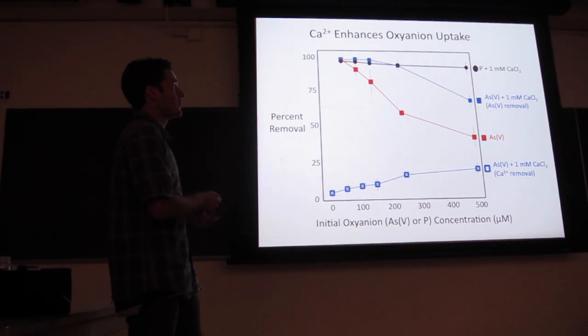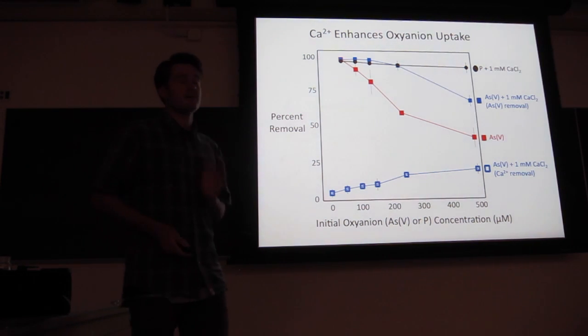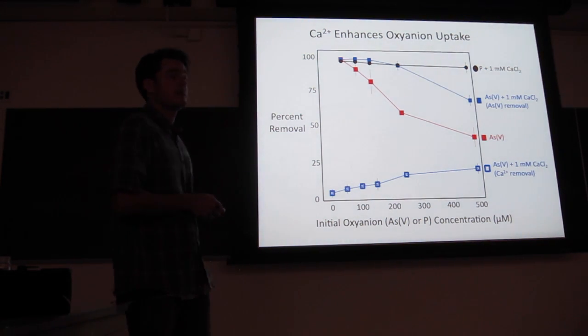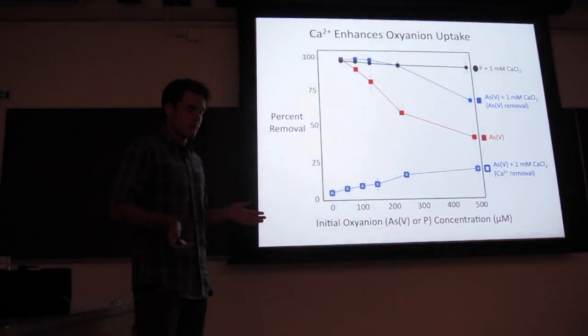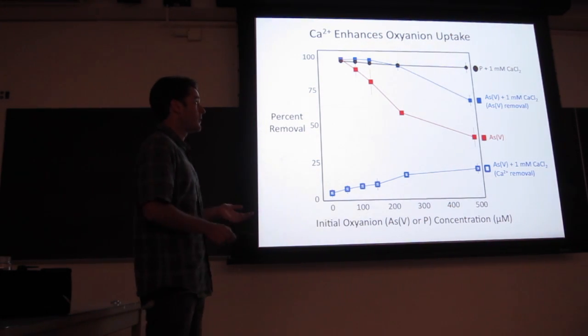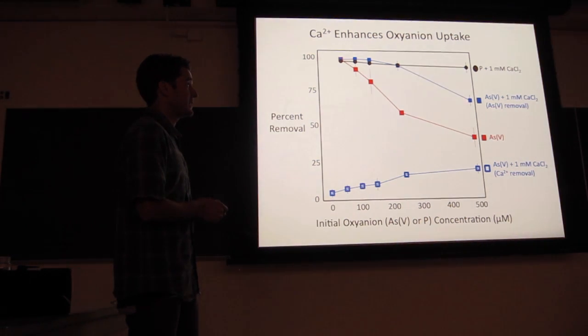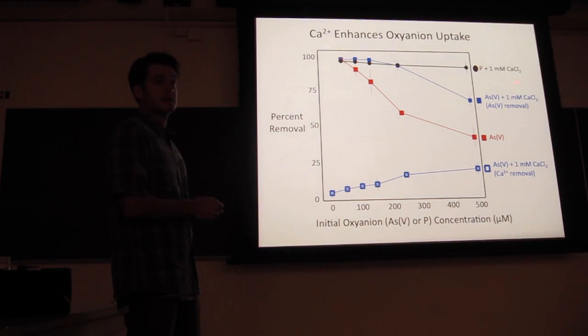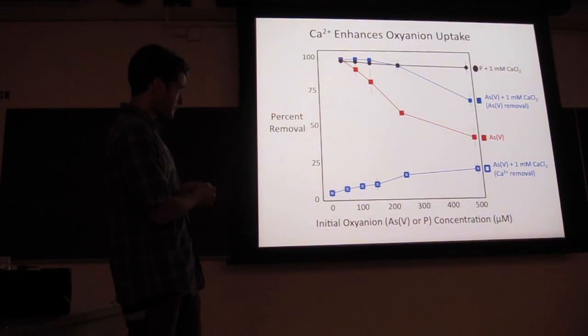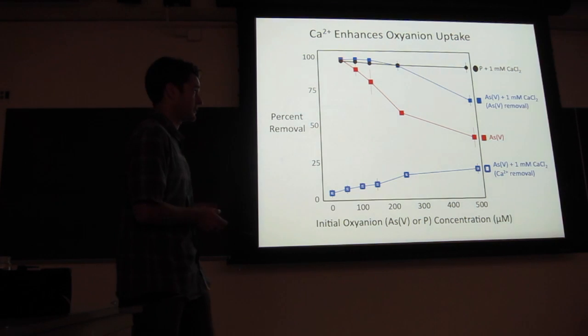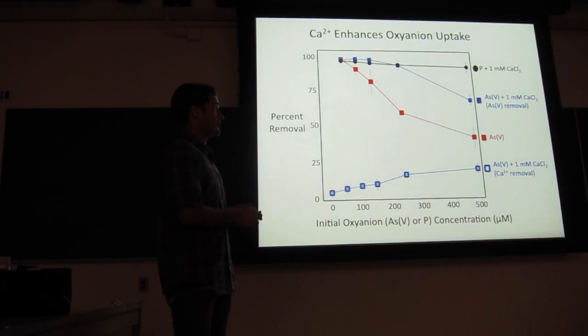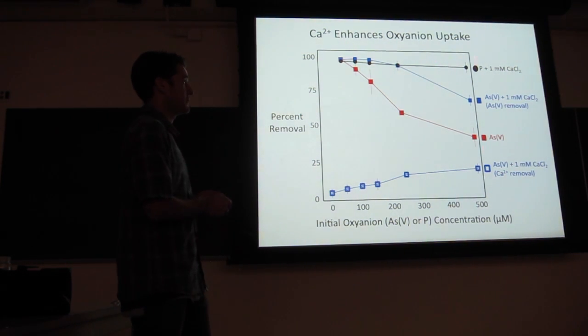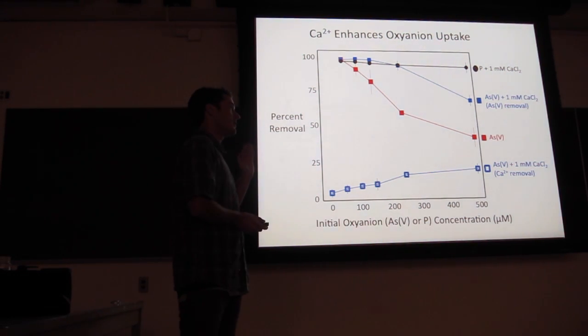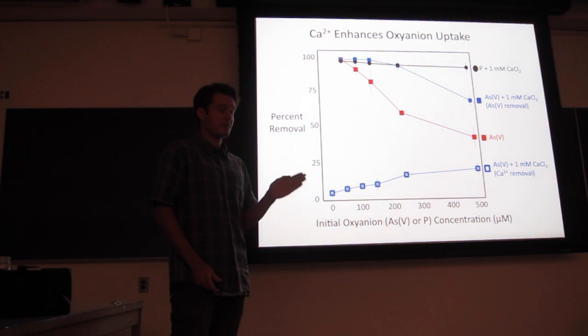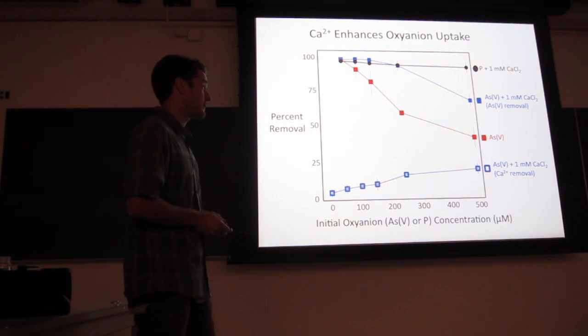So remember that in all of these experiments, we use the same amount of iron. So arsenic removal is enhanced in the presence of calcium, and that's our first indication that there might be an interaction between calcium and arsenic. But this interaction is going to be weaker than the phosphate-calcium interaction. So you see here that at every single initial phosphate concentration, we get nearly full removal. And so we can calculate the solids ratio for all of these samples. And for this sample in particular, we're looking at about a solid ratio of one phosphorus atom per iron atom. So it's an extremely high solids ratio.